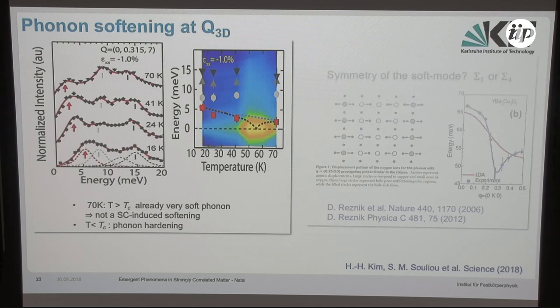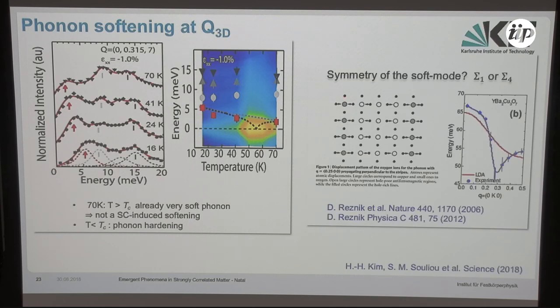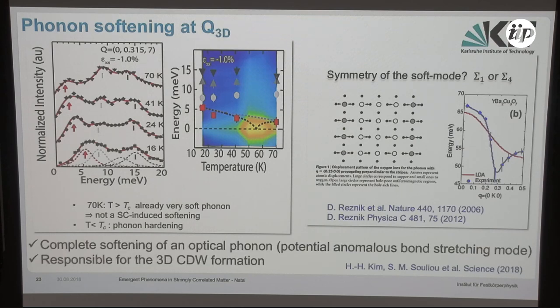And to finish, I cannot identify that mode, but I can identify the symmetry, and I know it has basically the symmetry of the so-called bond-stretching mode, which is a high-energy phonon that has a pattern that matches that of the stripes, and that was known for years to display a very anomalous behavior. Here is a bit more of the speculative part, but what we suspect is that with this uniaxial pressure, we can drive that mode to hybridize with the lower modes of the same symmetry, and drive it to complete softening, leading to the formation of the 3D order.